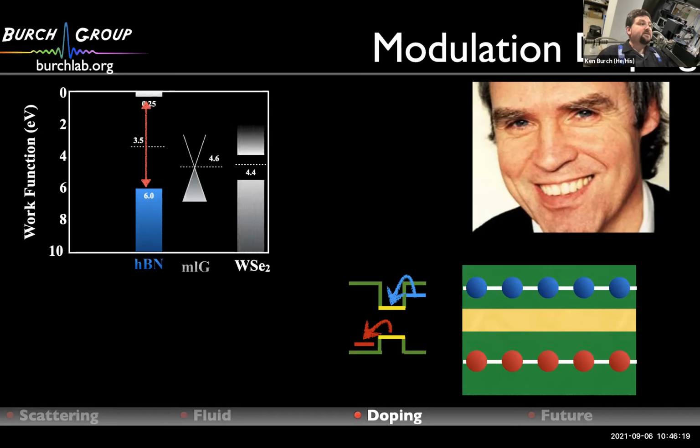You might ask about, say, tungsten selenide. Well, it has basically the same work function. So even though it has a smaller band gap, no love there. So what you'd like is a material with a small enough band gap, a deep work function, and perhaps a very narrow conduction band that is just sitting there waiting to soak charge away, right? And then you could think of it as what we would call a crystalline acceptor.